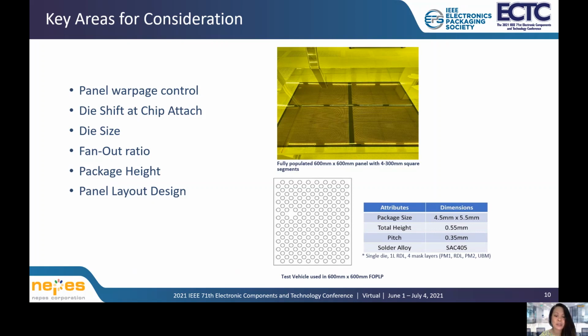Incoming wafer undergoes copper stud formation process, followed by wafer singulation, reconstituted onto a 600 millimeter temporary carrier prior to mold compression process. Die shift in X, Y, and theta is compensated during pre and post chip attach process prior to final mold compression process to ensure minimal die shift at mold dispense and mold compression. The temporary carrier is then debonded from the panel after mold compression process and undergoes a top grind process to expose copper studs.